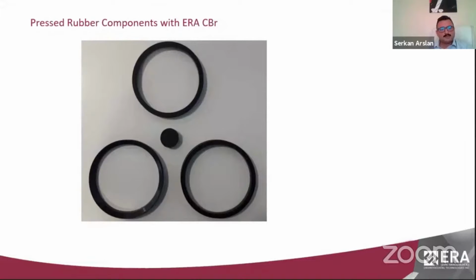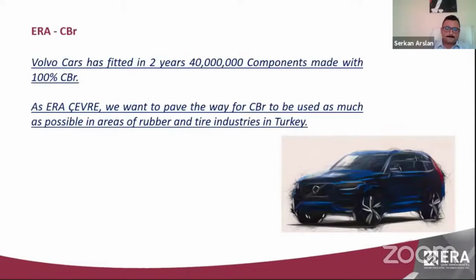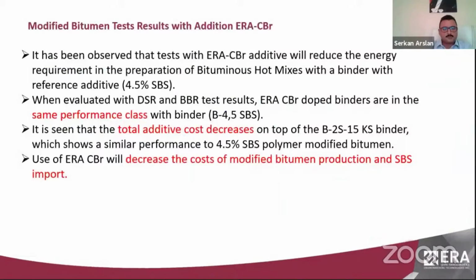You see here some pressed rubber components produced with ERA CBR. For example, Volvo Cars has fitted 40 million components in 2 years made with 100% CBR. And our aim is also that all the CBR that we produce can be used in production in Turkey, in tire production, in rubber production. So we have another research study. We tried our CBR carbon black in modified bitumen production, and we see that ERA CBR can be used as a modification addition for the bitumen, and that will decrease the cost of modified bitumen production and SBS import, which is used in bitumen production.